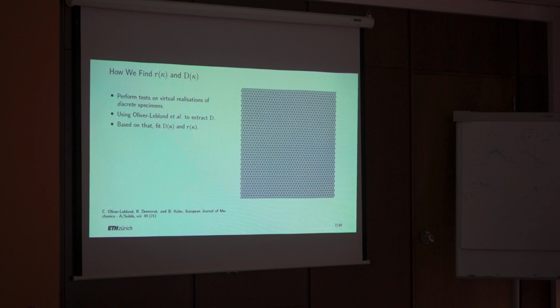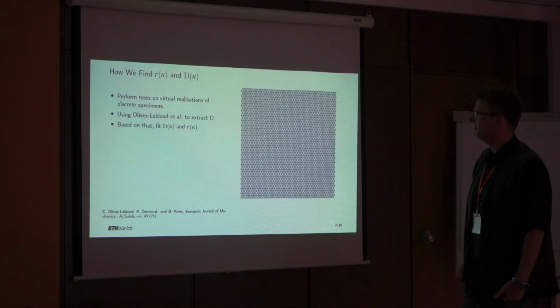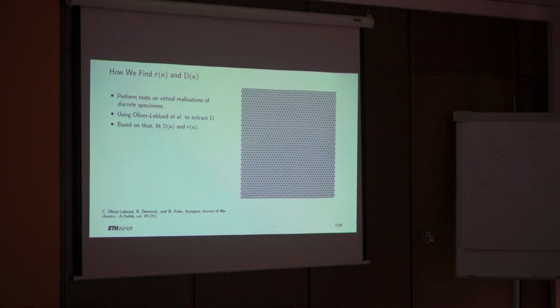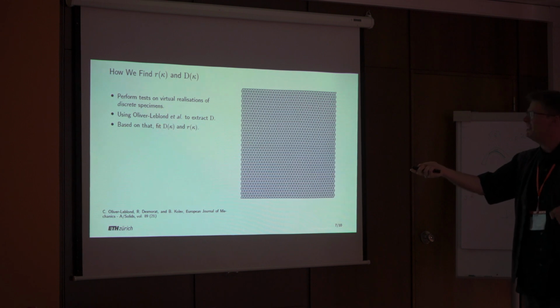I basically created lots of these specimens, a bit bigger, and then I basically subjected them to various tests. Also, I mean, I basically have pulled them apart until they fail. And then I have used this very nice paper by Olivier-Leblond that allowed me to extract d from these measurements. And then based on that data, I was able to fit representations for d and R.